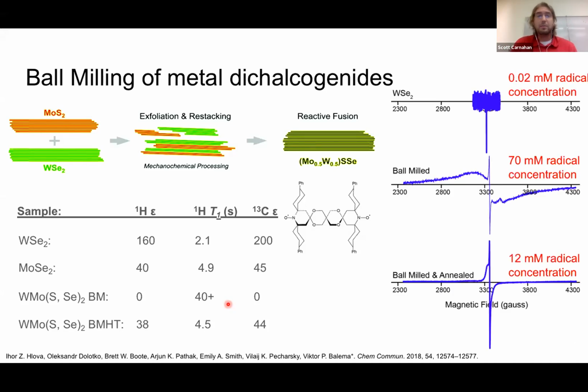So we tested this by EPR. Tungsten selenide by itself really didn't show much radical concentration at all. But after ball milling, we see a large amount of radicals created with an extremely large g anisotropy. After the annealing step, the g anisotropy shrunk, and the amount of radicals also reduced. So we're really starting to understand what this harsh ball milling procedure does to samples, and this is something we want to look into further.